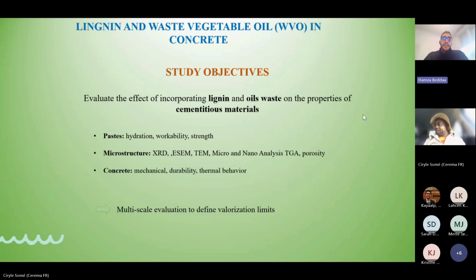And the last axis is about concrete. We will extend this study to the concrete scale in order to see how we can incorporate these two additives for a real application, and then evaluate this concrete based on these additives. So evaluate their workability, their compressive strength, the durability of this concrete, and also the thermal conductivity, in order to see the limits of the incorporation of these additives, and also to see the reuse potential of these additives in reality.